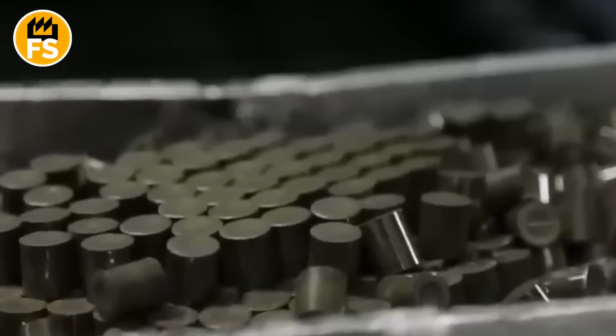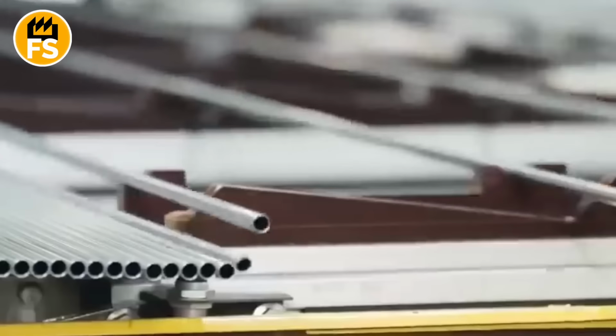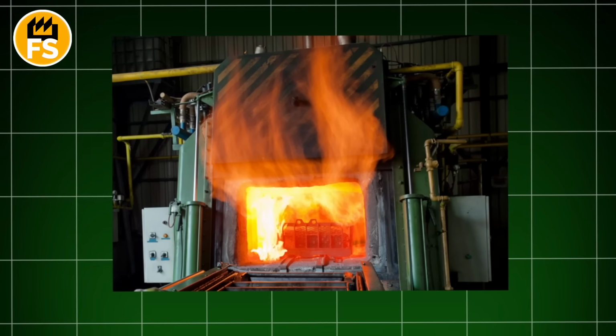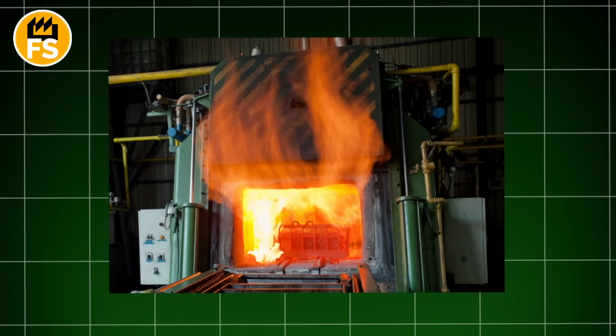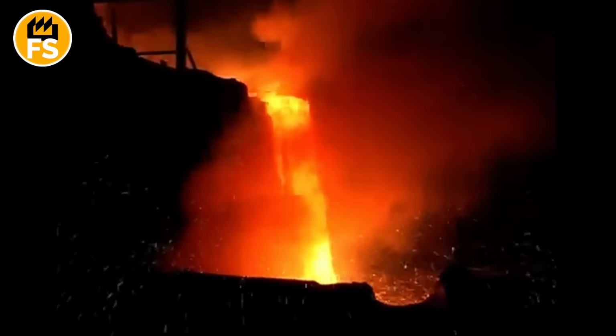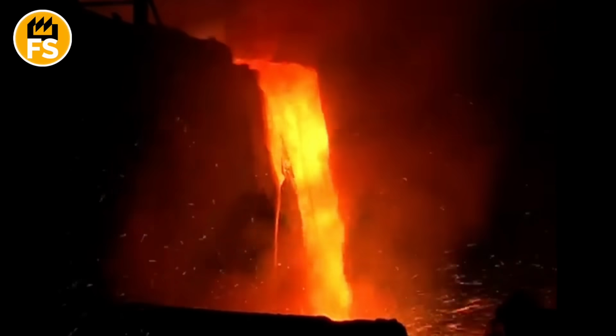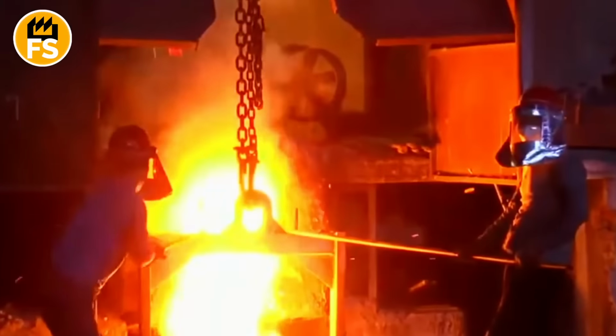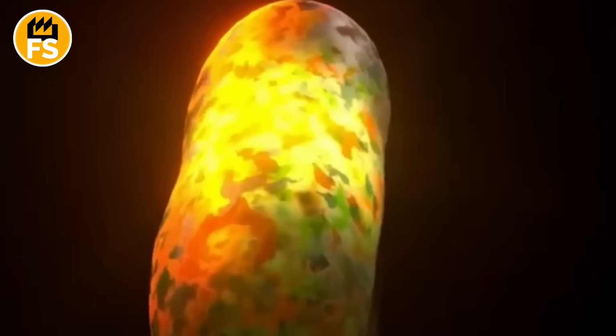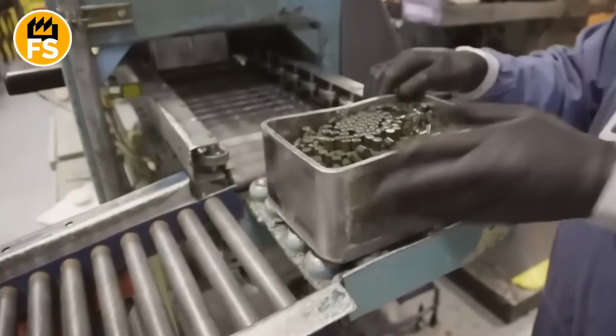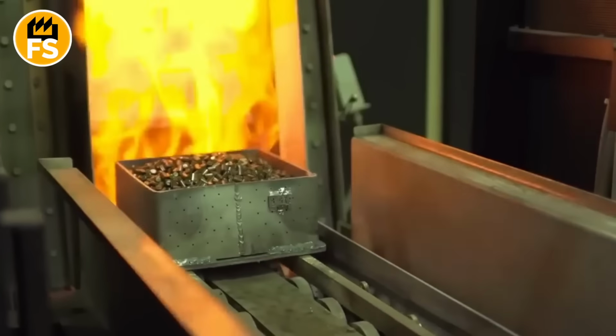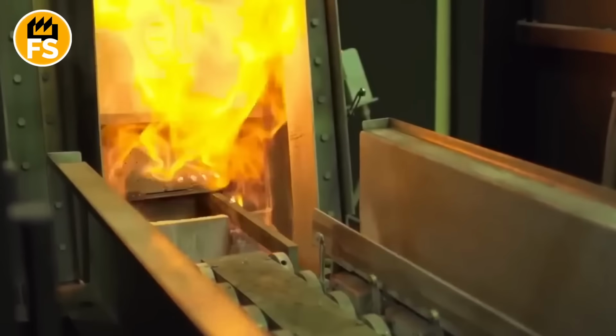They are still brittle, like chalk. To give them strength, they are sent to a furnace. But this is not an ordinary furnace. This is a high-temperature furnace, filled with hydrogen to prevent oxidation. There, at a temperature of over 3,000 degrees Fahrenheit, these pellets are baked for many hours. During this process, called sintering, the powder particles fuse together, and the pellet turns into an extremely hard, dense, ceramic-like substance. It becomes so strong that it can withstand the extreme temperatures and pressures inside a nuclear reactor.